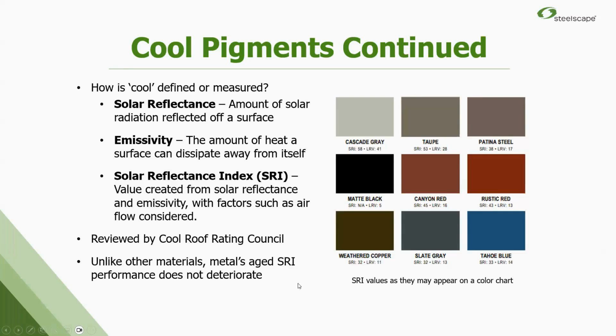The Cool Roof Rating Council double checks us on all that, and then we do aged results as well. I like to talk about the aged results of our product because these products are formulated not to fade or change over time. They hold their initial SRI value very, very well. So you're not going to get any drop off in that energy efficiency performance over time with painted metal like you would with asphalt shingles or single ply membrane coatings that degrade pretty quick.